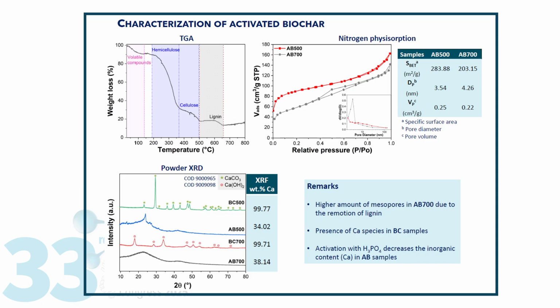Characterization of activated biochar. Thermogravimetric analysis of agave showed a considerable weight loss at 500 degrees C due to the removal of hemicellulose and cellulose, while at 700 degrees C, the weight loss was due to lignin. This led to the creation of a greater amount of mesopores in sample AB700. On the other hand, XRD analysis showed the presence of calcium species in the BC samples, which were largely eliminated after the activation treatment.